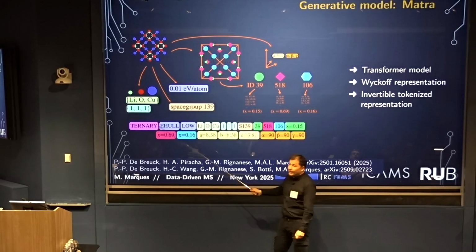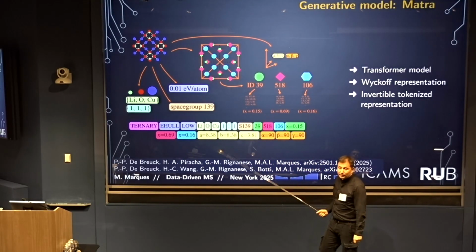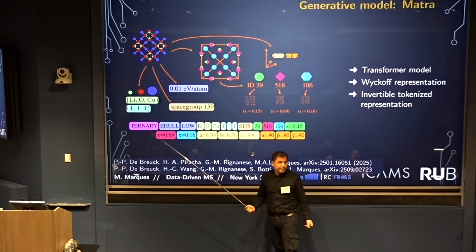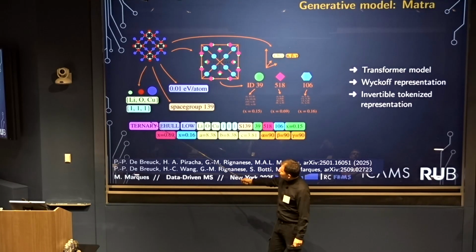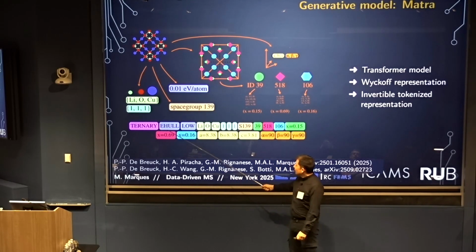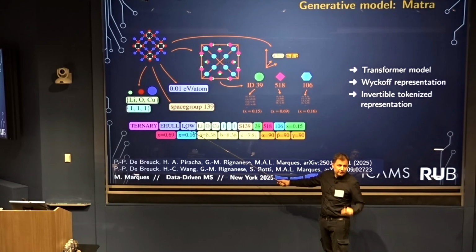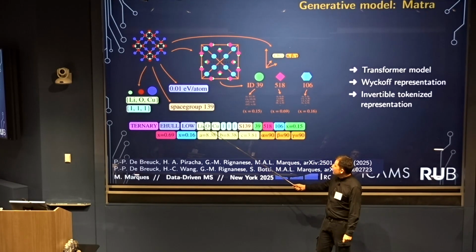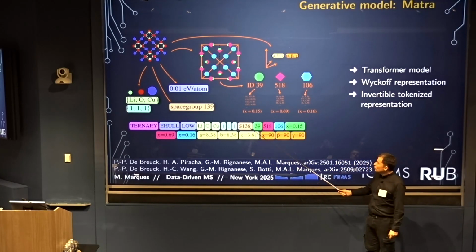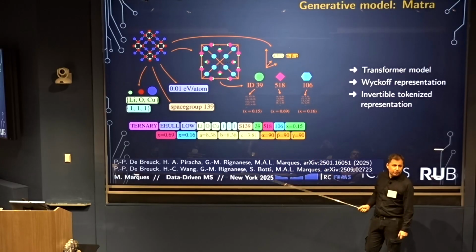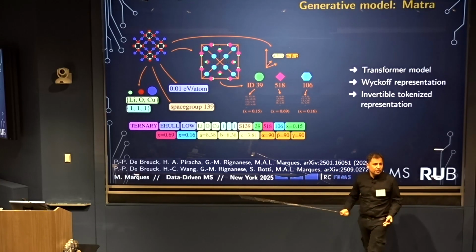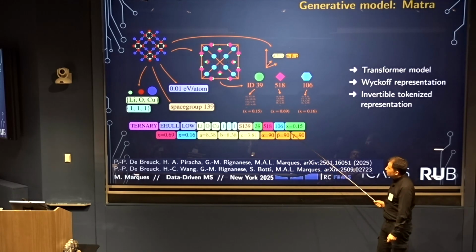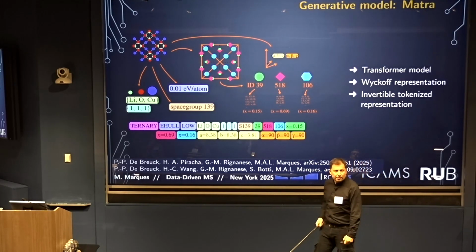We use a string to code what the material is. And this string is based on symmetry, on space groups and Wyckoff positions. So you will see right away. For this thing that is here, we start by saying it's a ternary compound. E hull low means it's close to thermodynamic stability, so in the training set. Then it has lithium, oxygen, copper in the ratios 1, 1, 1, in space group 139, and this is a code for the Wyckoff positions. And then go the free parameters. Each space group will have a certain number of free parameters, and each Wyckoff position will have a set of free parameters. And here they are. We do this to the few million compounds we have in our database.